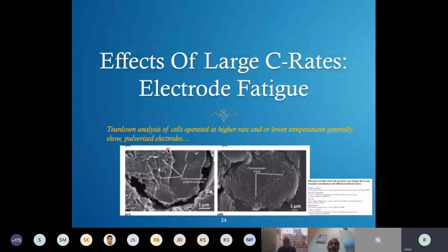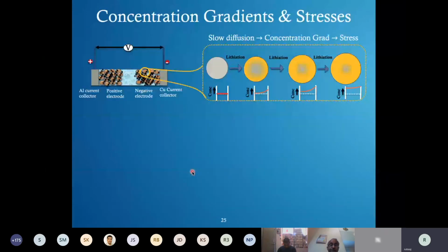Going back to physics, basically when we are charging and discharging, again we are lithiating from the outer surface. As we lithiate, if we assume that this yellow is the lithium concentration, there would be a higher concentration of lithium atoms outside, and these lithium atoms would gradually diffuse in towards the center. Initially there is no concentration, then there would be a concentration gradient. What it means is there is higher concentration outside and lower concentration inside, and the concentration gradient would be different at different stages of usage. Also, it will depend on the diffusion coefficient of your electrode.